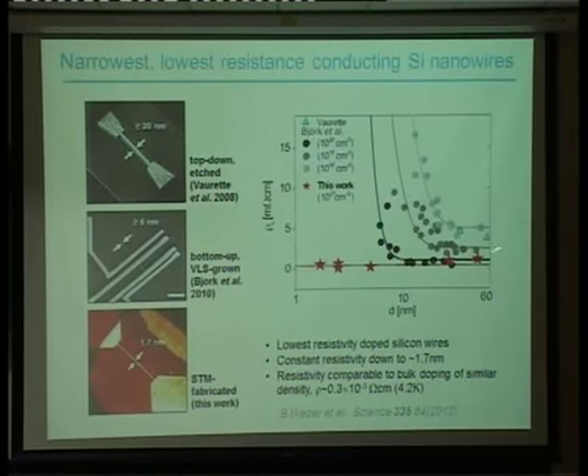But the interesting part now is if we measure the resistivity of these wires as a function of the diameter. These are the red stars that you see. You can take it all the way down towards the atomic scale, and the resistivity stays the same. Now, this was really, I guess, unexpected at the time because a lot of people were measuring silicon nanowires and finding below about 10 nanometers, no matter how much they increased the dopant density of their structures, the resistivity shot up to infinity.